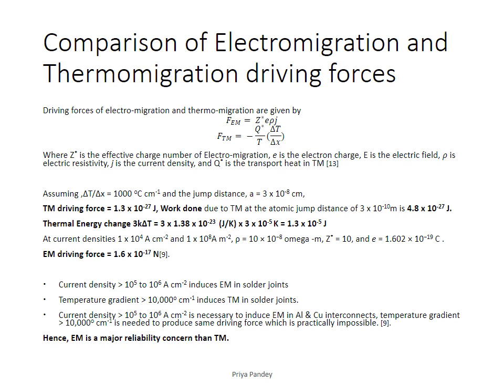For electromigration in aluminium and copper interconnects, a current density greater than 10 to the power 5 to 10 to the power 6 ampere per centimeter square is typically required. This means that we need a temperature gradient larger than 10,000 degrees Celsius per centimeter to provide the same driving force, which is too high. Hence, thermomigration hasn't been a reliability concern in aluminium and copper interconnect technology.